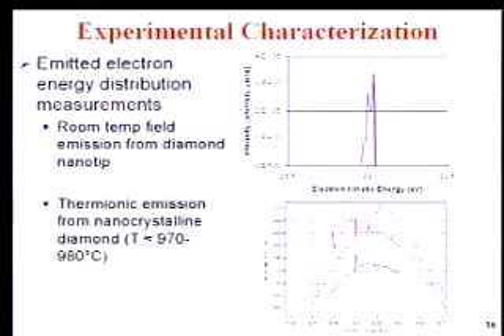Just to wrap up, I promise to be done in time. We're doing experiments on this where we are measuring the energy distribution of emitted electrons, both by field emission and by thermionic emission. I won't go into too many details, but certainly we see some evidence from very small tip emitters. These are from diamond. Both of these are nanocrystalline diamond materials, where we see shoulders in the distribution. In this case, this may or may not be real. It was somewhat repeatable. And then down here, we can get to very finely resolved energy distribution measurements, and we're in the process, we've been doing these for only about a month, of ferreting out the experimental noise from what might actually be physically true.